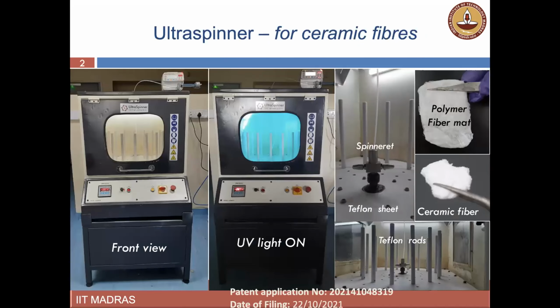We have also recently, in this process, developed an ultra spinner. We call this an ultra spinner, but it's a simple centrifugal spinning setup with a UV light possibility, where you can make polymer fibers, fiber mats you see here, and we convert them into ceramic fibers. Not typically meant for structural applications. In fact, we filed the patent only yesterday. So we are able to make such polymer fiber mats and convert them into ceramic fiber mats. Not meant for structural applications, but they could be used for several functional applications possibly.